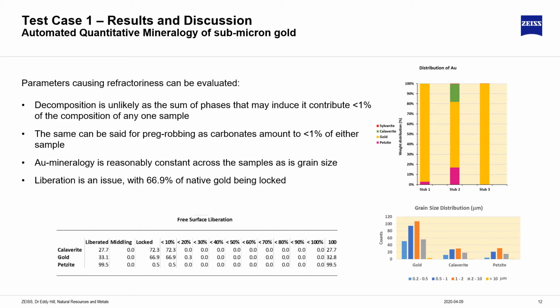Now, with this information, we can consider the parameters causing refractoriness. We can evaluate them. And we find that decomposition is unlikely, as the sum of phases that may induce it contribute less than 1% of the composition of any one sample. There are hardly any copper sulfides, for example, in these stubs. The same can be said for preg-robbing. The level of carbonates present is below 1% in either sample. The gold mineralogy is reasonably constant across the samples, as is its grain size. However, liberation is an issue, with 66.9% of native gold being locked.